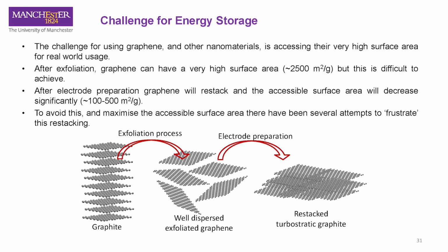It's not graphene's fault. It's the way that we're trying to use graphene and integrate it into our application without modifying the way we actually do that. So what we need to do is prevent that restacking, or frustrate it somehow. People have done things like crumpling these graphene sheets up like a sheet of paper, or having other materials in there as well. So maybe, going back to what we've learned about synergy, by having multiple materials in there together, we can prevent that restacking occurring.